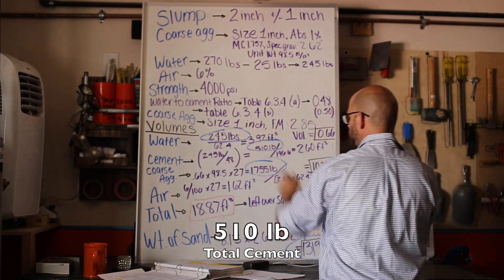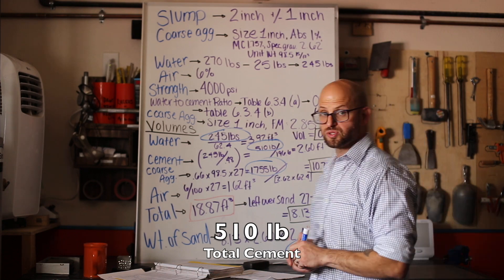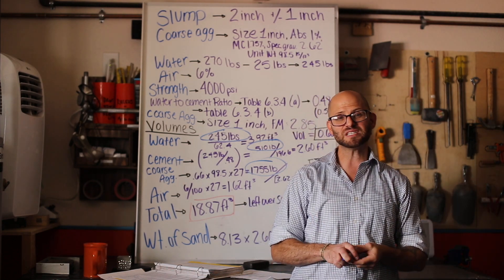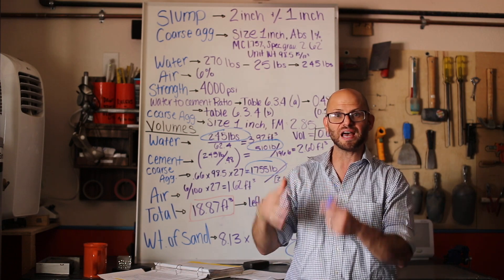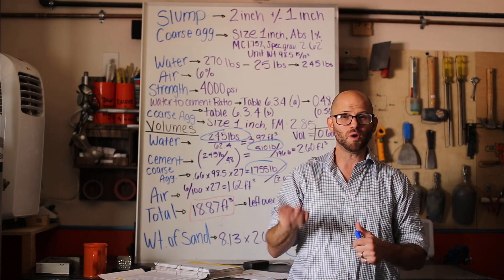These are our final weights. We got 1,319 on our sand, 1,755 on our rock, 245 pounds on our water, and 510 pounds on our total cementitious. That's our mix design.